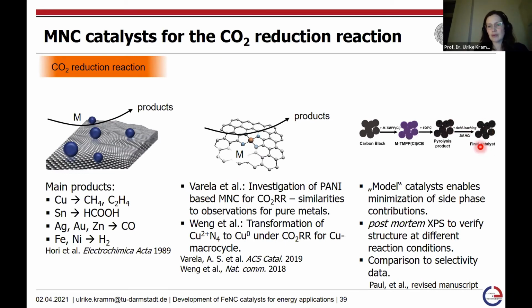So these catalysts were investigated in an electrochemical setup with a gas diffusion electrode connected with a mass spectrometer, and also then by postmortem photoelectron spectroscopy in order to verify the structural changes during the reaction conditions, and basically then to compare also the data that we obtained to the selectivity data. So this is a manuscript that is currently under investigation, with Stephen Paul as first author, but it's a joint work with some other people from the Helmholtz Center in Berlin and from the Fachhochschule in Mittweida.